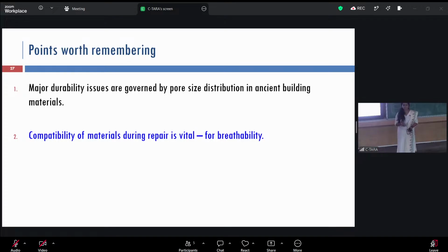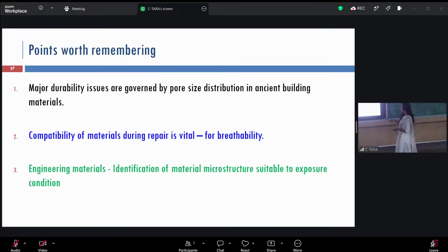Second point is, when you're repairing a heritage structure, the most important parameter is breathability or compatibility of materials for breathability. If a structure is inherently breathable, you cannot block the breathability. You should choose a repair material which is very similar to the existing material. And the last point is, depending upon the exposure condition, you engineer your material or choose your material.